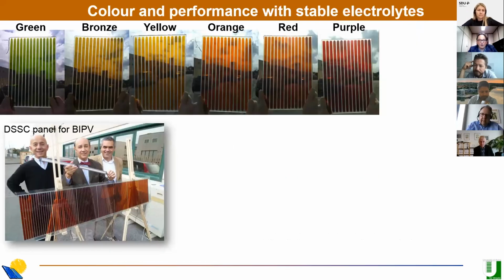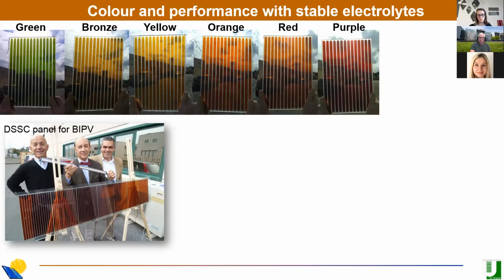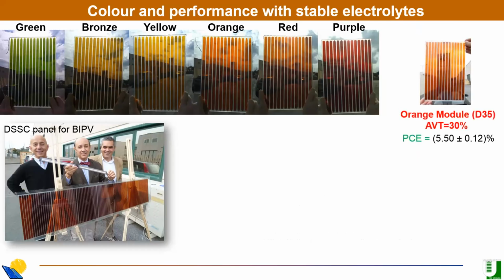This is more or less what you can get. It's not too transparent, but at that time we had some other milestone related to colors. And then you see you can change color more or less continuously from green to red. Still blue is a bit problematic. And this is the typical value of efficiency, around 5.5% on the module level, and AVT around 30%.